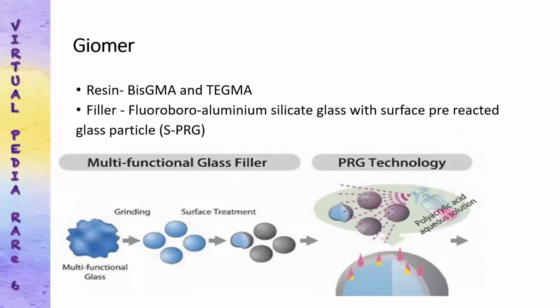Giomer is a modification of compomer in which the glass filler particle is coated with the polyacrylic acid. So it has got a pre-reacted glass in which the polyacrylic acid coat is there over the glass, and on which there is a coating of silane. This silane coating helps us to join the filler particles with the matrix, and pre-reacted glass particle is also helpful to release fluoride in ample amount. So it gives anti-caries effect with the fluoride releasing property, and it has got resin matrix for imparting the strength.